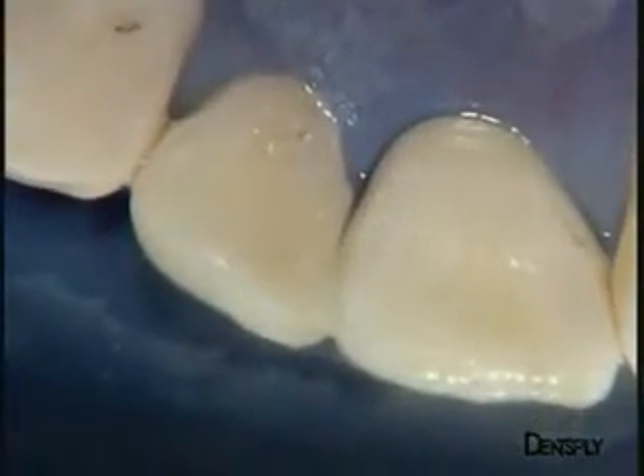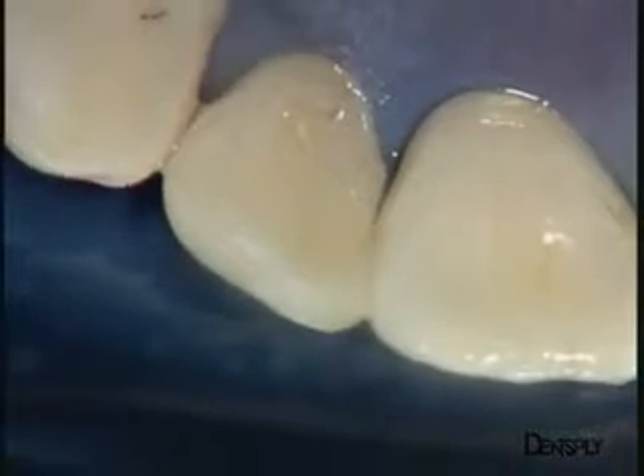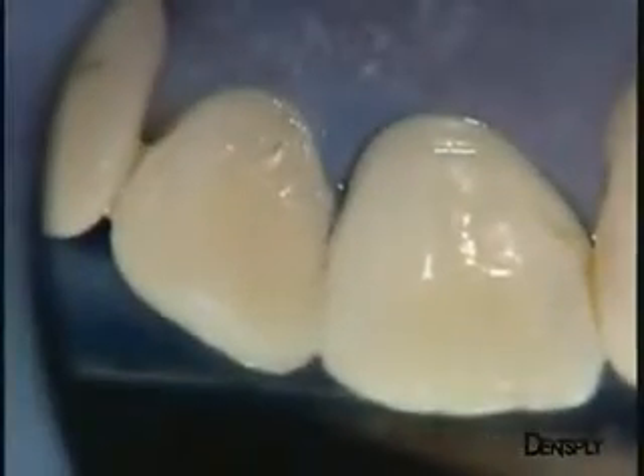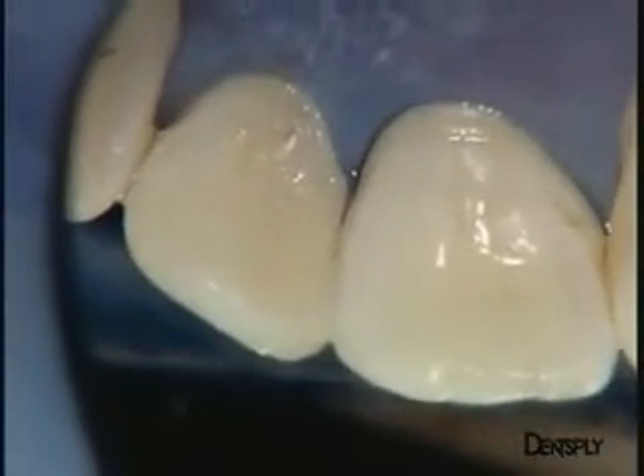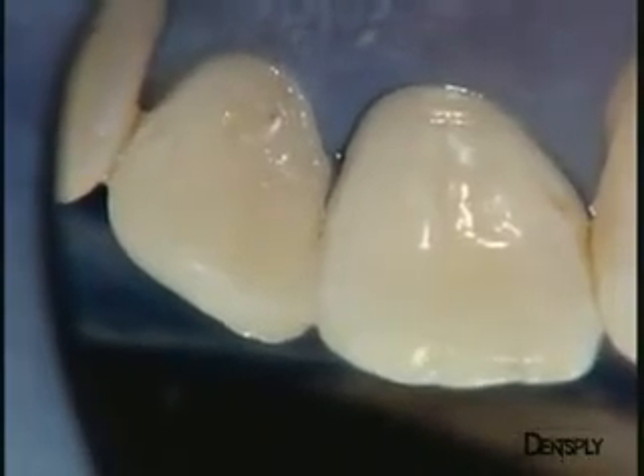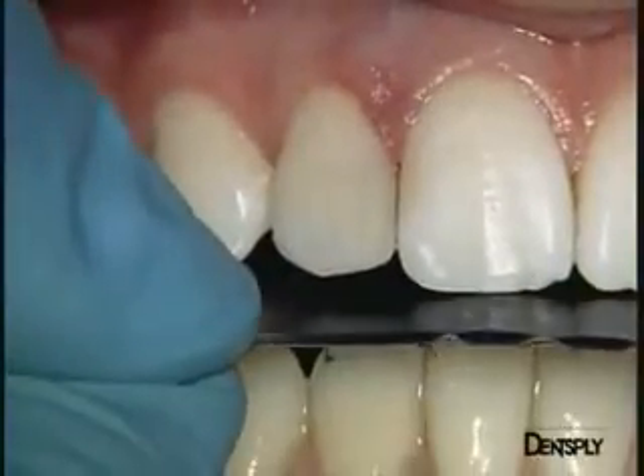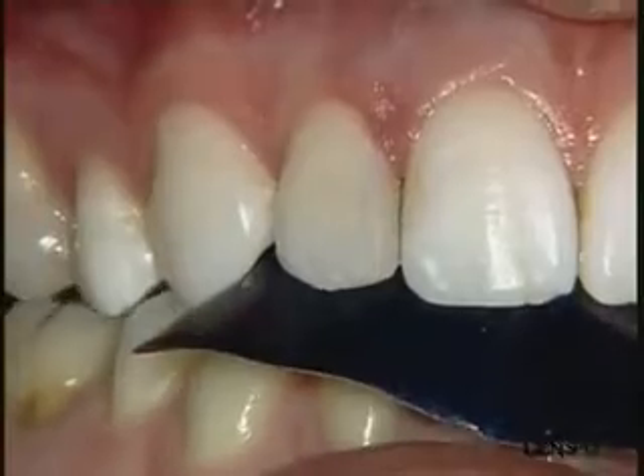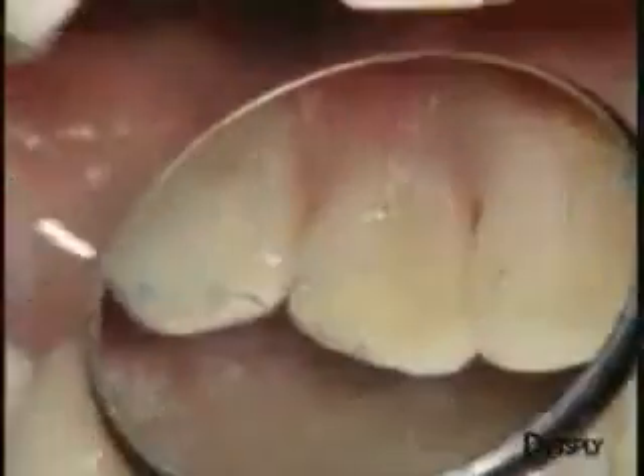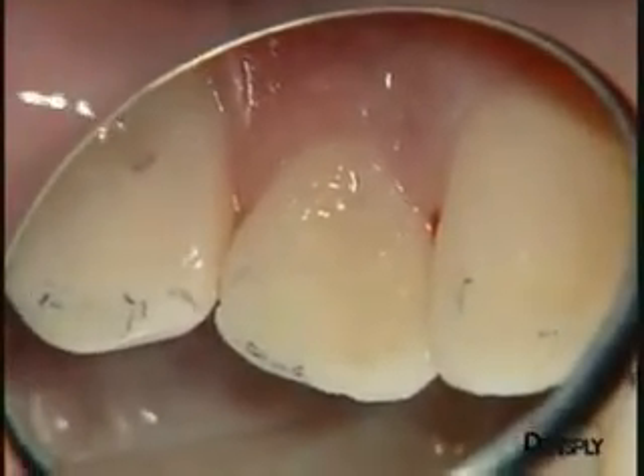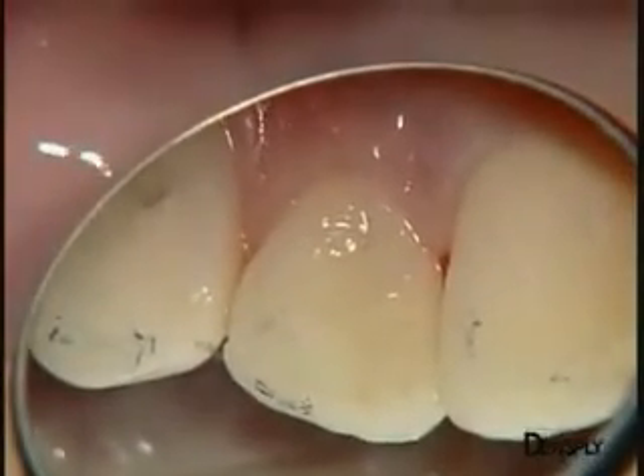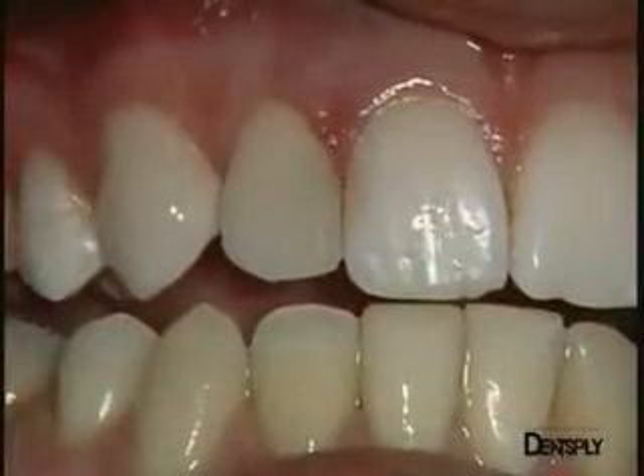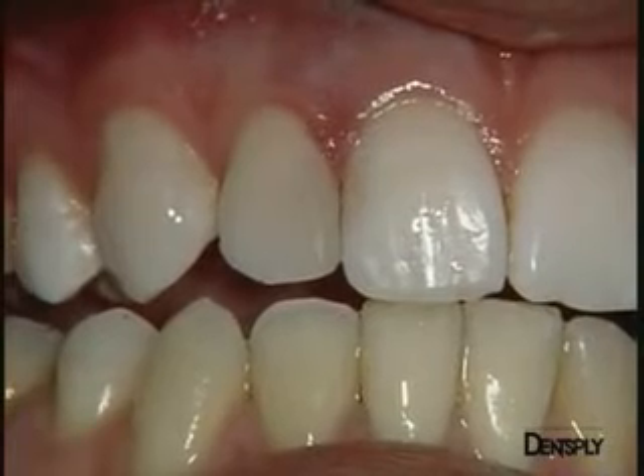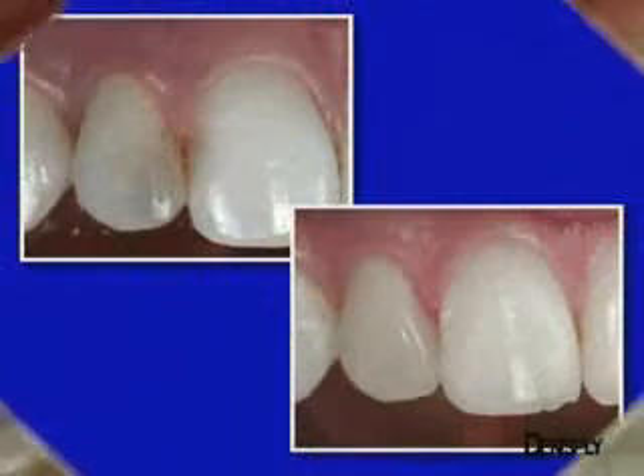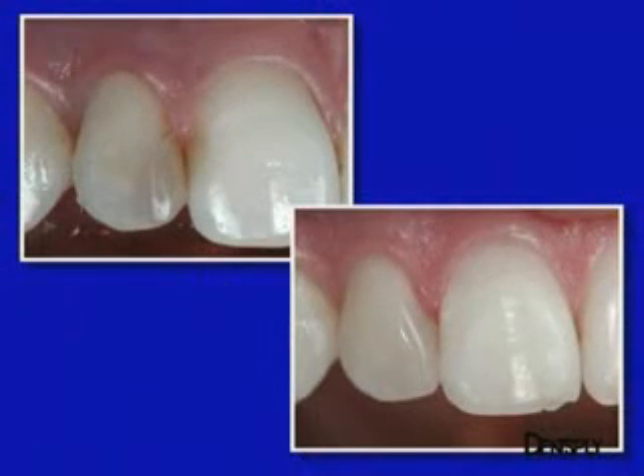In the lingual view, we can see that the stratification imitates the dental anatomy well and reproduces the colour effects of the natural tooth. Once the operative area is cleared, it remains to check the filling and remove any excess. Here, you see that thanks to the key and the build-up of the lingual wall, there is only little excess of composite, and here is the result just after the removal of the rubber dam. Once again, we see that, with a simple stratification of Ceramex Duo, a satisfactory aesthetic result is obtained.